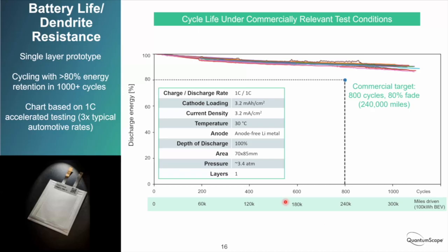This is cycling data from batches of our single layer pouch cells in this form factor. And it is, I think, one of the most impressive demonstrations of dendrite resistance that our cell offers. So I'm showing the discharge energy on the y-axis and cycles on the x-axis here. The commercial target that Volkswagen has set for us and that we're setting for ourselves is 800 cycles to 80% fade. For context, a typical EV warranty today would be somewhere between 100 and 150,000 miles to 70%. So somewhere where my cursor is right here. We're trying to get to this 800 cycles to 80% target here.